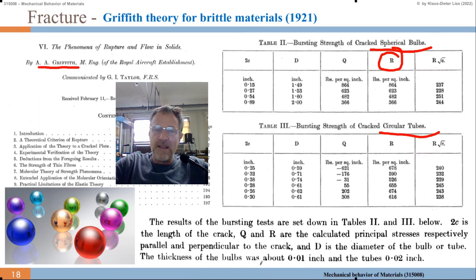The thickness of the bulbs was about 0.01 inch—homework to convert that to millimeters. And the tubes were about 0.02 inch.